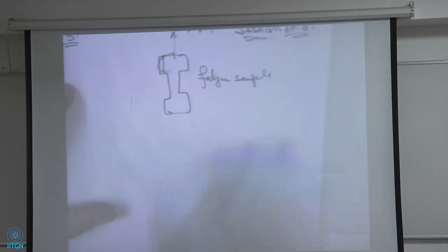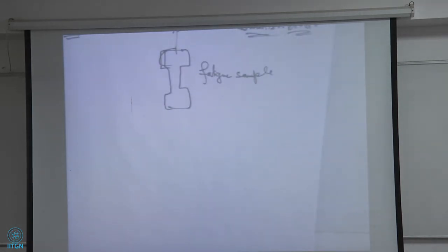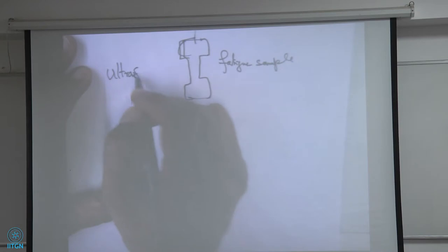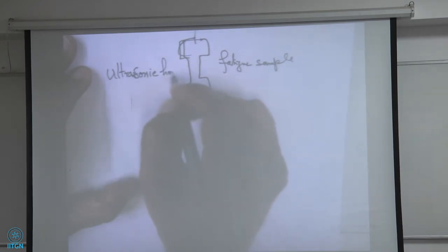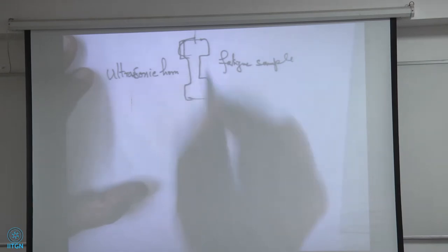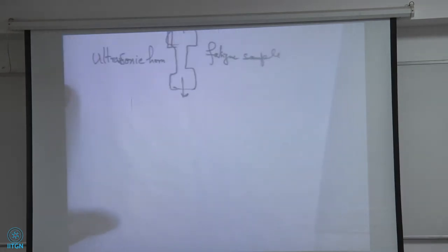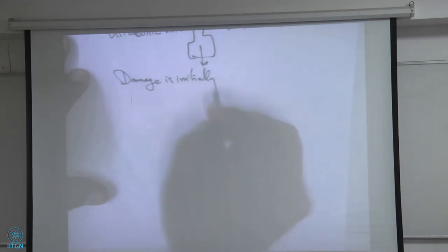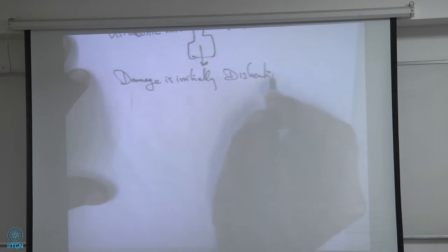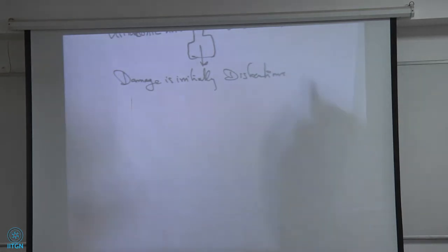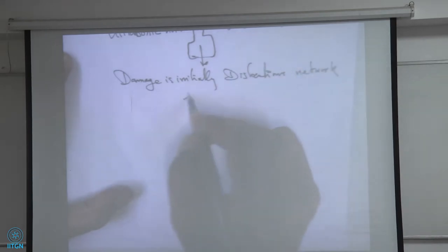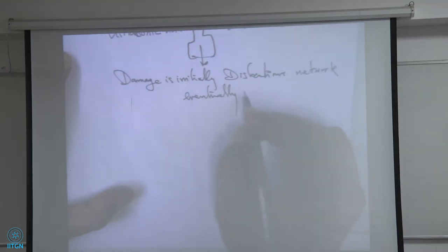Okay? So what we did here is, there is something called an ultrasonic horn. So we are fatiguing it, so damage is being created inside it. The damage is initially dislocations. A lot of dislocations are being generated and they're forming these networks, dislocation networks, and then eventually a crack will appear.